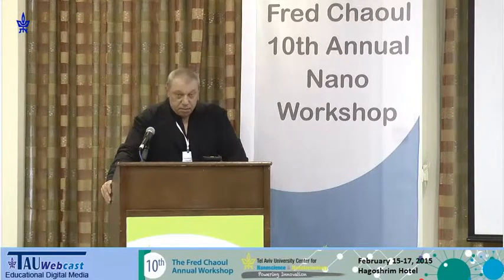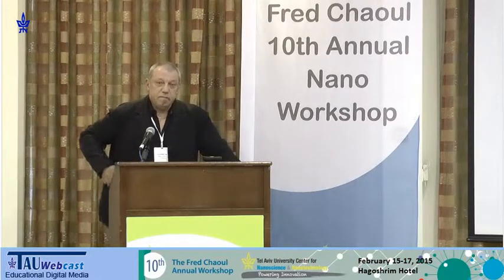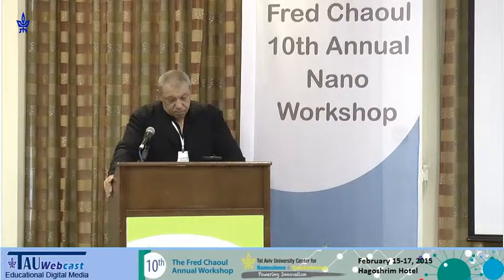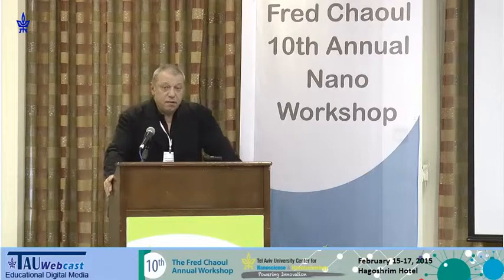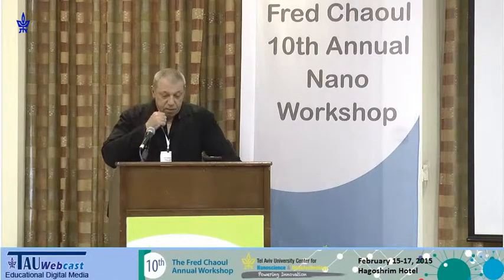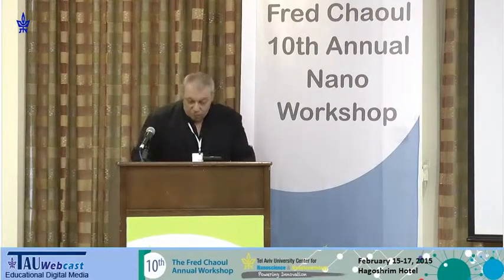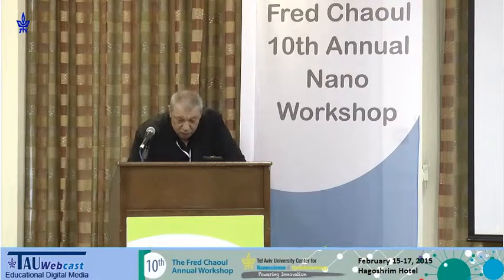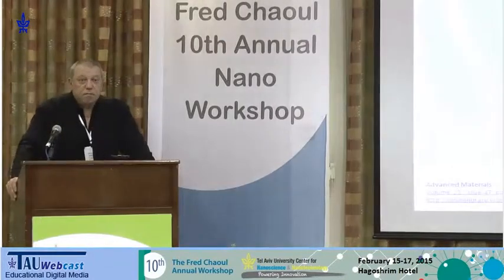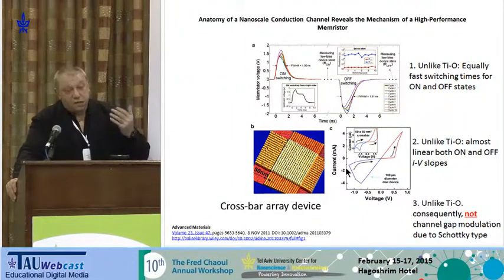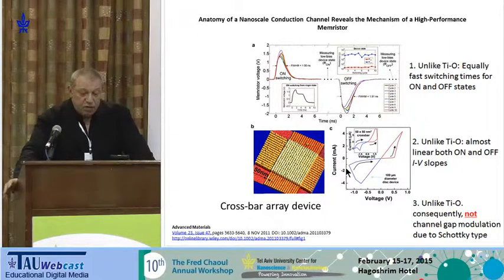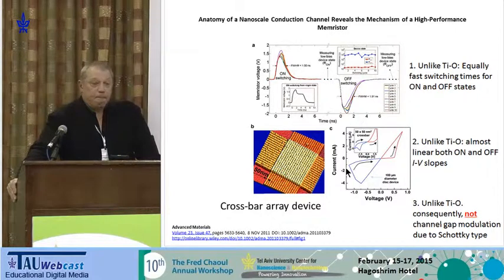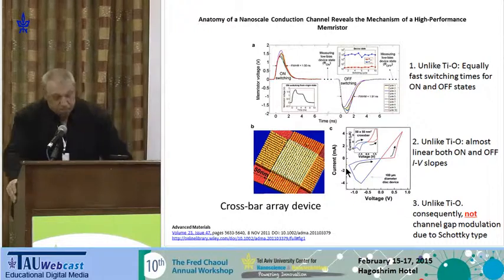Question about oxygen migration under double charge versus thermal effects. The memory is very, very non-volatile: once oxygen is out, we have the on state with very low resistance — to get it back, you need to move it from that state. We think it's a combined electric and thermal field: electric field vertically between the electrodes and thermophoretic motion annularly. Let's thank our speaker again.